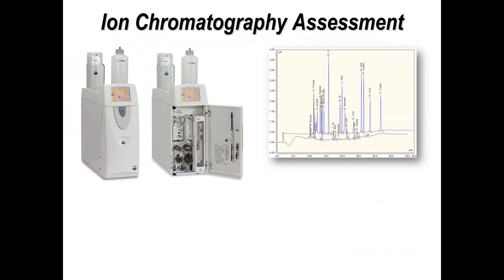Ion chromatography is basically a CSI-type approach — you get a numerical value for the level of contamination, but also the ability to identify what that particular contamination is from the surface of the printed circuit board. You can take a board assembly and put it into a plastic bag with a chosen ionic testing solution — not the cleaning solution you'd use in a cleaner — and measure the result. This is similar in technique to the original ionic contamination testing, but far more detailed. NPL has conducted testing on ion chromatography, and there is some information available from our defect database.